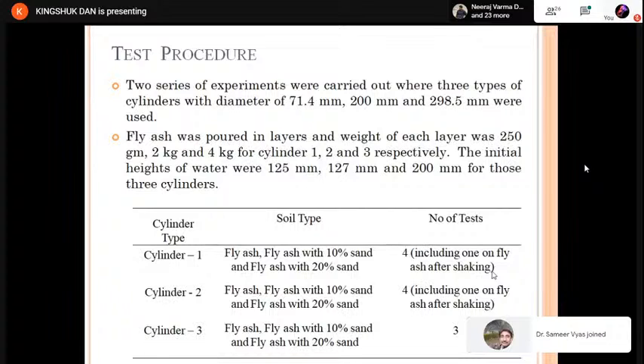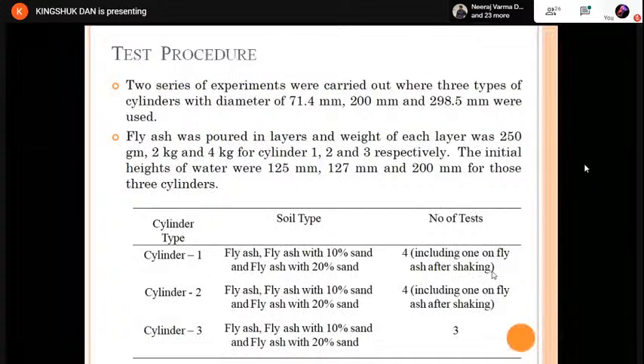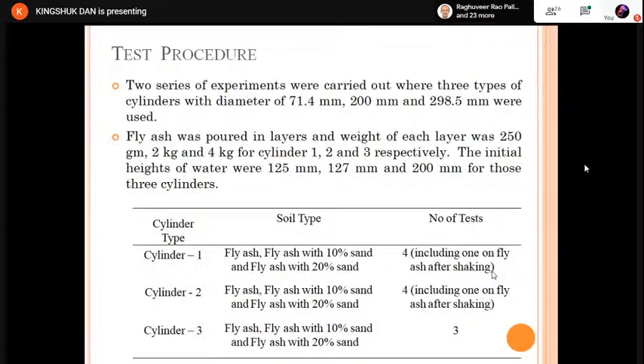Two series of experiments have been done here, where three kinds of cylinders are used with different diameters, that is 71.4 millimeter diameter, 200 millimeter, and 298.5 millimeter diameter. In the first series of experiments, all three kinds of cylinders are used, and for each cylinder, we have conducted three tests: using fly ash, fly ash with 10% sand, and fly ash with 20% sand. For cylinders 1 and 2, we have done an extra test using fly ash after shaking, where it is attempted to see the settlement behavior, dry density and water content profile of fly ash after it is flowing with high forces.